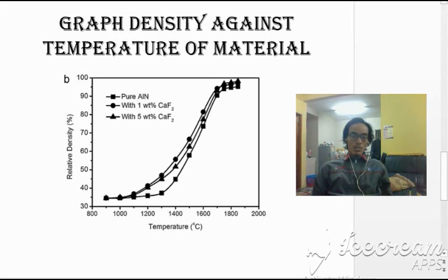As you can see here at 900 degrees Celsius, the starting point, it increases to the maximum until 1800 degrees Celsius. The curve of the pure aluminum nitride represents this material. So we can see the density is increasing as temperature increases.